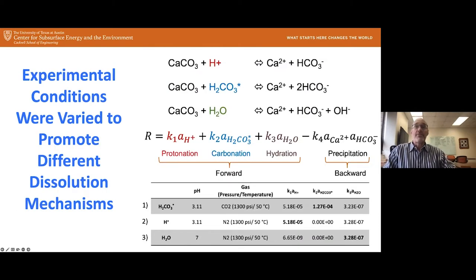If you haven't read much about calcite dissolution and precipitation, it's often argued, and then shown experimentally, that in the system we're looking at, dissolution can be controlled by reaction with proton, reaction with carbonic acid, or reaction with water. The rate of dissolution is often expressed as a function of those three parameters, or I should say the activity of the proton, the activity of the carbonic acid, and the activity of water. Depending on those activities, if we exceed the activity of calcium and bicarbonate, we can have precipitation. In our case, we have only dissolution. We don't get high enough concentrations for precipitation, so I just worry about the first three terms.